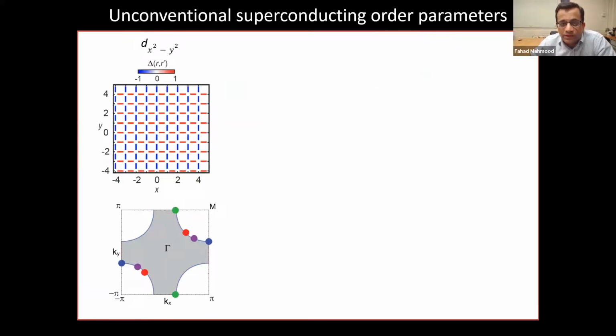What we did is we tried to understand what this double ARPES would measure for 3 different superconducting order parameters. One was a d-wave superconducting order parameter here. So here you have pairing, and this is still pairing across opposite sides of the Fermi surface. So pairing between these red points, between these purple points, or these blue points at the antinode. Okay, so those are the points that are paired with each other, but not these points here, the green points.